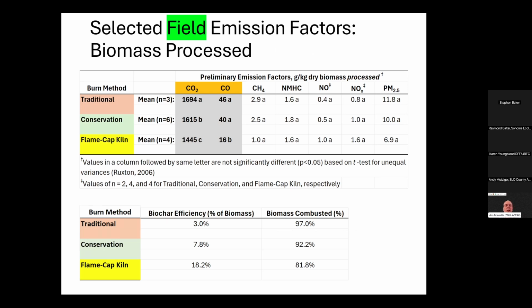And so when you do that, you sharpen your differences a little bit, because the flame cap kiln, for example, had the highest amount of biochar produced compared to the other two. Conservation burn was a little bit better than the traditional, but you see a very clear difference now in terms of total CO2 coming off between the three methods. And then also carbon monoxide again retains its significance.